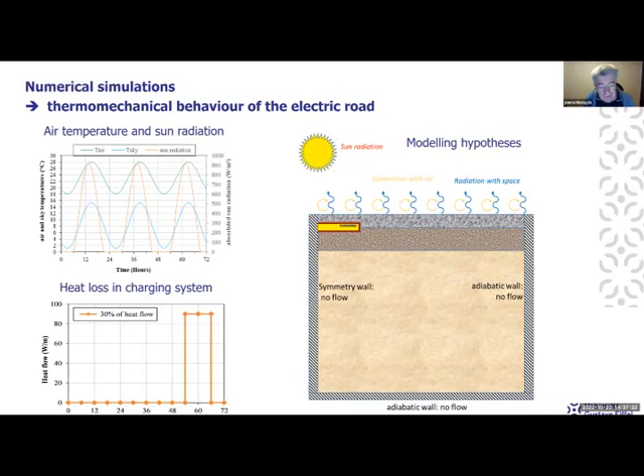We did it first separately for the thermal behavior and the mechanical behavior and the traffic loading, but it would be desirable in a second phase to do a coupled thermomechanical modeling. So for the thermal modeling, we were interested mainly in hot temperature conditions, because for the asphalt layer, what is important is to know what maximum temperatures will be attained in the system. And so we simulated temperature variations corresponding to summer conditions.